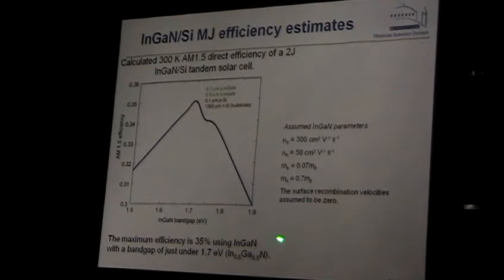So we did some calculations. These are more realistic calculations. These are not detailed balance calculations. These are assuming some realistic material properties. So you see that if you take indium gallium nitride with the gap of about 1.7 electron volt, and silicon, on silicon you can get efficiency of 35%.